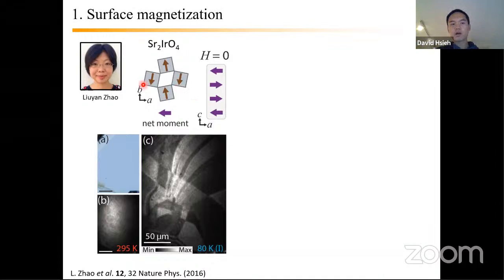And so you can see that this slight canting leads to a net moment given by this purple arrow. And the stacking of this purple arrow, this net moment along the C-axis, is staggered in a left-left, right-right, left-left fashion, at least in zero magnetic field, okay? So if you were to do, for example, an optical Kerr effect measurement, there's no net magnetization to couple to, but with surface sensitive SHG, you can actually couple to the top layer and monitor that magnetization on the top layer.